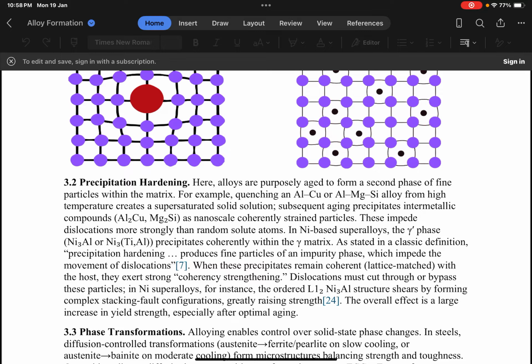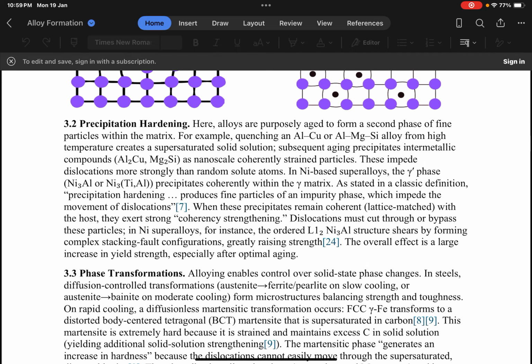In nickel-based superalloys, the gamma prime phase, nickel aluminium or nickel titanium aluminium, precipitates coherently with the gamma matrix. As stated in a classic definition, precipitation hardening produces fine particles of an impurity phase which impede the movement of dislocations. When these precipitates remain coherent, lattice matched with the host, they exert strong coherency strengthening. Dislocations must cut through or bypass these particles in nickel superalloys. For instance, the ordered nickel aluminium structure shears by forming complex stacking fault configurations, greatly raising strength. The overall effect is a large increase in yield strength, especially after optimal aging.